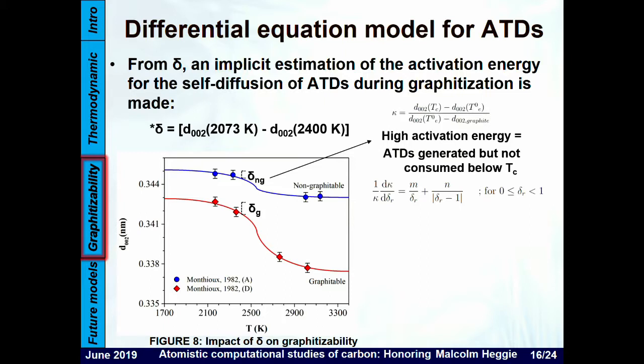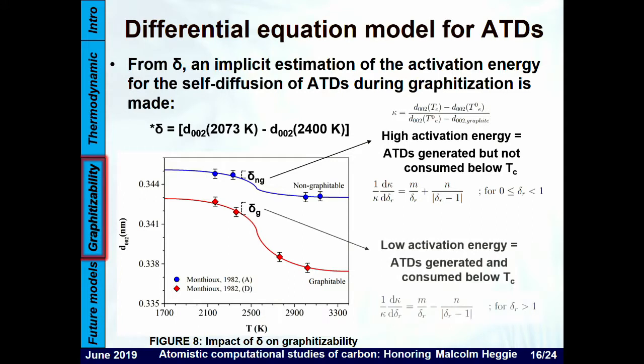So this is more or less what the differential equation will look like if the ATDs are generated but not necessarily consumed during the critical region. That's why the delta is very small. If the delta is much larger, the differential equation will change. Yes, some defects will be generated by merging, which is represented by this term, but they will also be consumed. This is why the negative sign is applied here, and this is why here we have a positive sign.